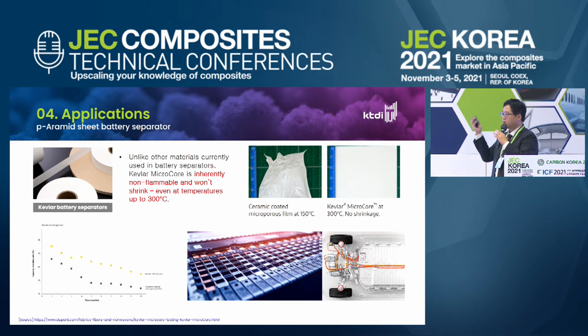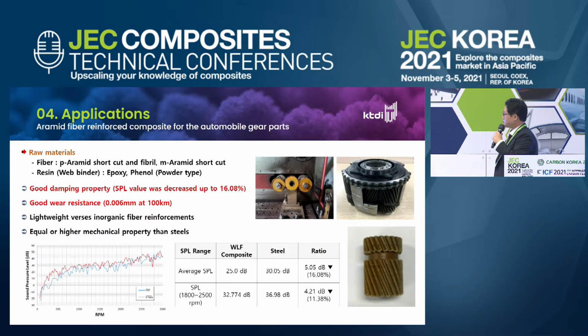And when you go to the webpage of DuPont, you can see that electric batteries are actually an important area. And in 2019, they launched a battery membrane. They do the ceramic coating on the battery film. And it was weak. It wasn't flame resistant or heat resistant, but they were able to create Kevlar, which has no shrinkage and which is a much more improved product.